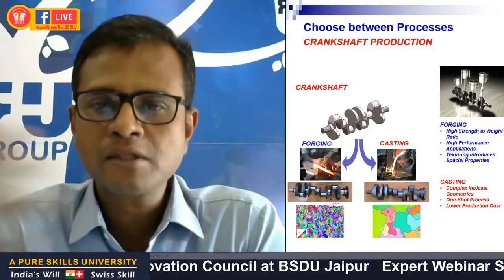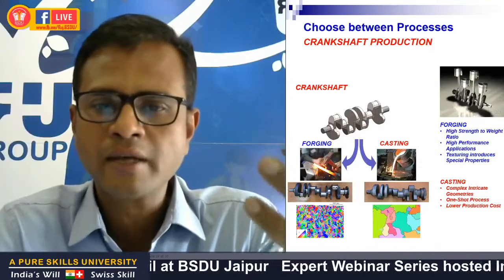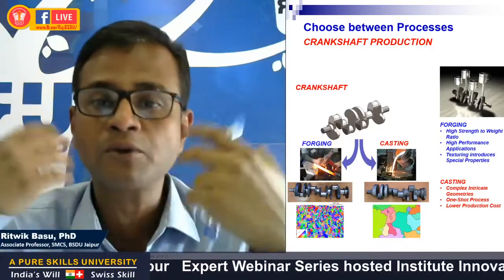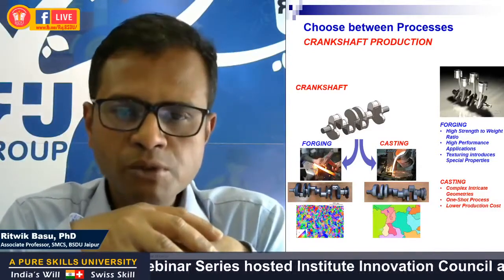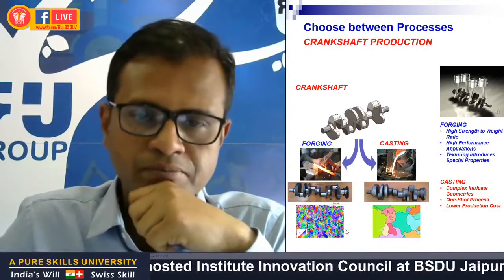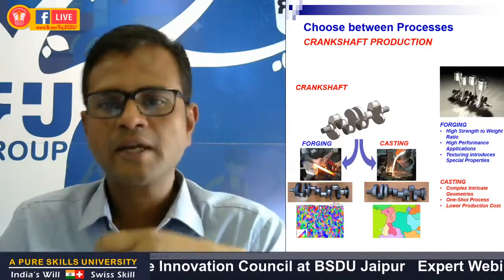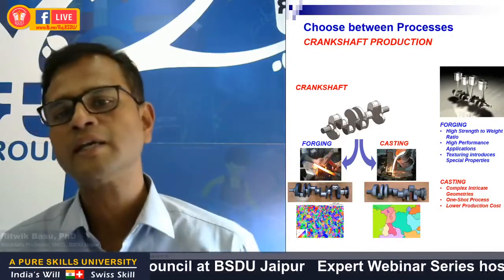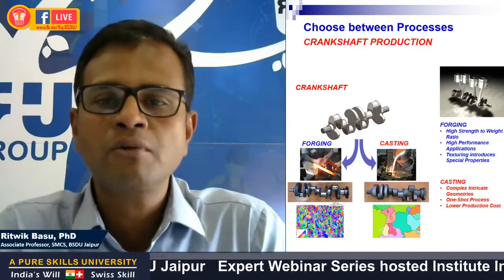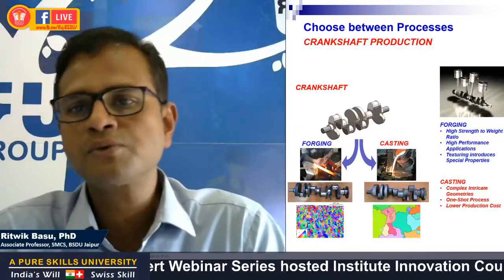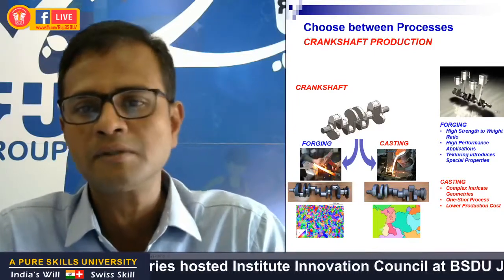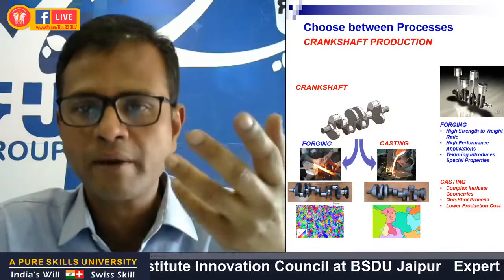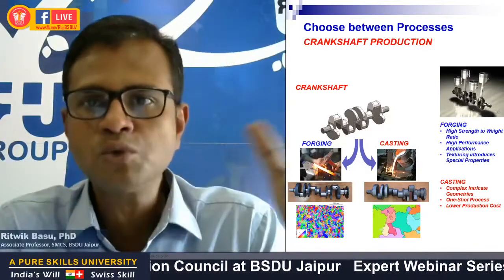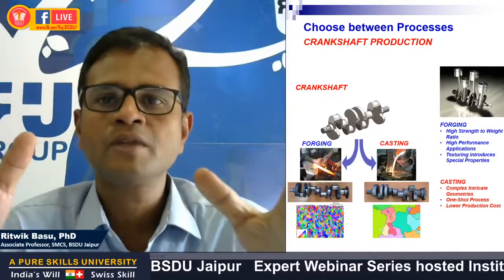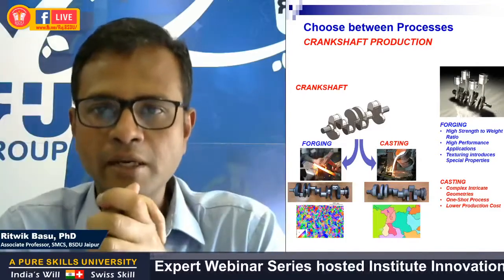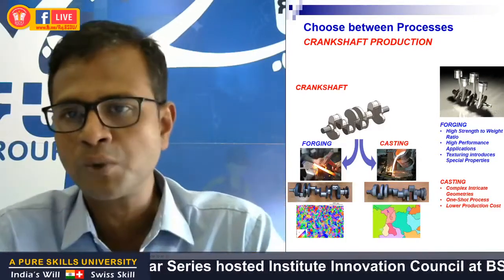But what brings a difference in the properties between the cast and the forged microstructure is again understood from a microstructural perspective. So as could be seen, forged microstructure exhibits texturing as well as fine distribution of grains that leads to grain boundary strengthening and partly anisotropy that makes it superior for many high strength applications. Whereas cast crankshafts are good for applications that require a high abrasion resistance or wear resistance. So therefore, when there are various processes available, you have to make a judicious choice from a microstructural standpoint. And the crankshaft example is the best example to showcase this.